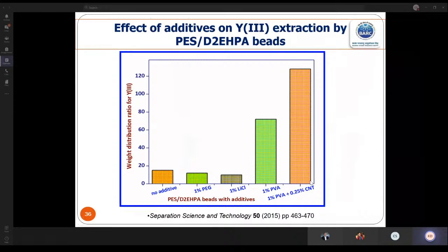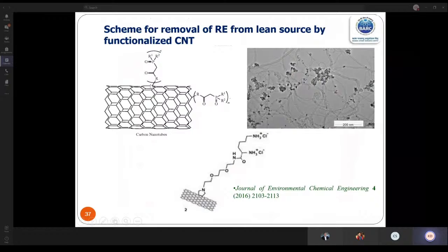So what is the role of the carbon nanotube? Basically, carbon nanotubes modify the pore structure, as well as they get functionalized and they absorb the rare earth material. So typically, carbon nanotubes get functionalized with ligands which are specific to the rare earths. And here in the transmission electron microscopy, you can find these rare earth metals getting deposited on the carbon nanotube. And this is specific, means if there are other metals, the other metals will not come. It is the rare earth which can come. So we can selectively take the rare earths in the carbon nanotube.